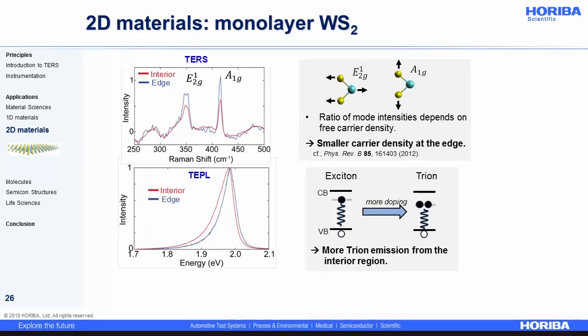Also, by looking now at the average tip-enhanced photoluminescence spectra of the central part and the edge of the flake, we can see that the PL narrows and is shifted to higher energy within the edge region. So, for the same reason, the smaller carrier density at the edge, and in contrast, we have a larger carrier density in the interior of the flake where more trion emission is seen.